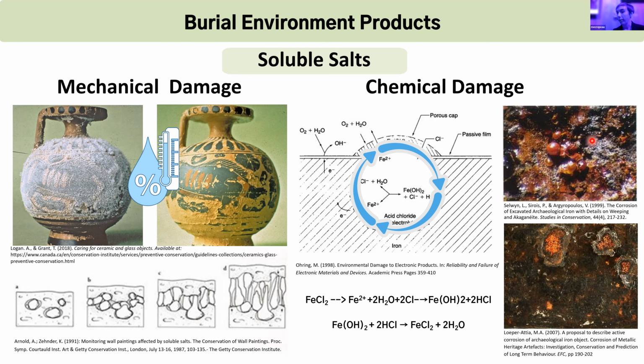And to that point, you often get what we call corrosion blisters. This happens as a result of that acid corrosion, where you have a pit that is formed because it's being dissolved by really concentrated, localized pinpoints of hydrochloric acid. It's also building almost a blister or bubble around itself, so it's like trapping this chemistry inside. And when you pop these blisters, you end up with these rather ugly looking holes, these craters in your artifact from this chemistry that's occurring. So soluble salts are definitely a big problem. They cause a lot of both chemical and mechanical damage to the artifacts post-excavation.